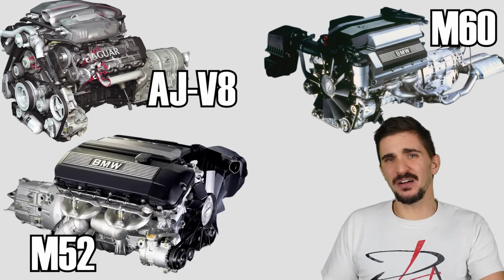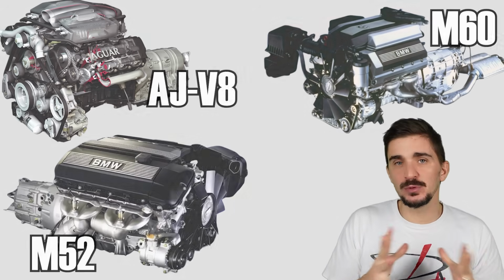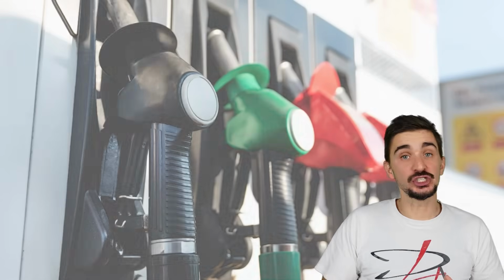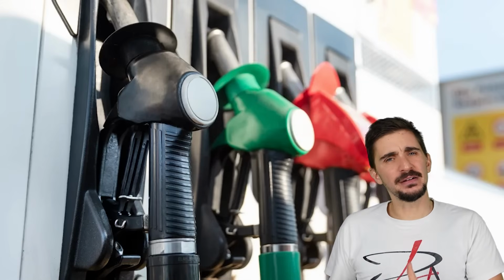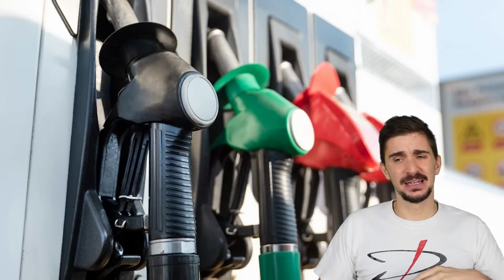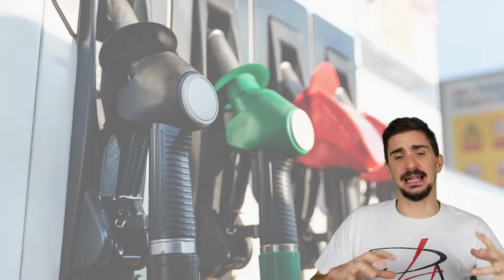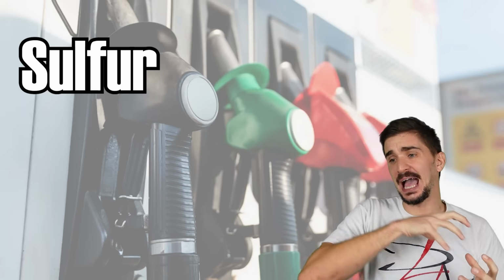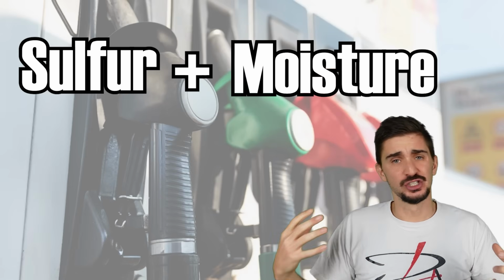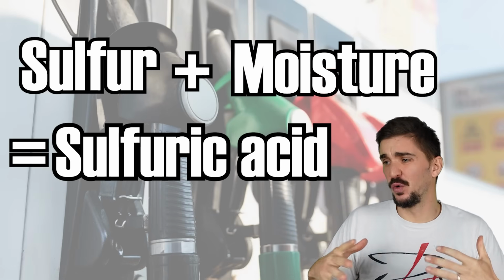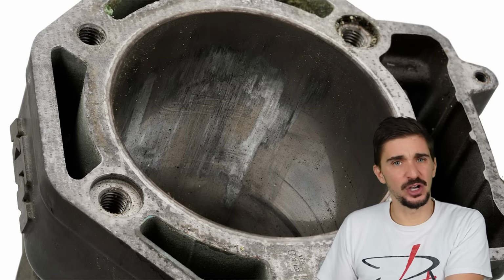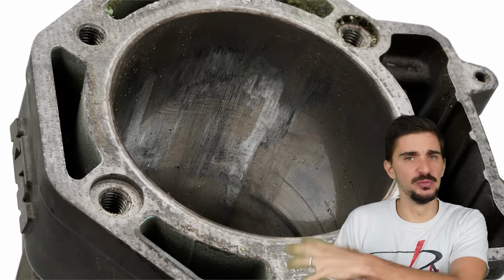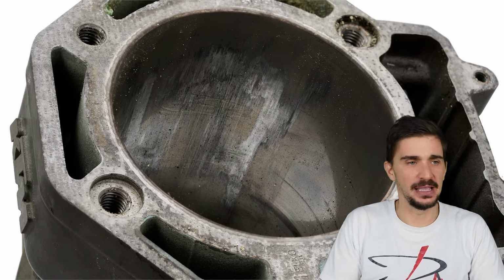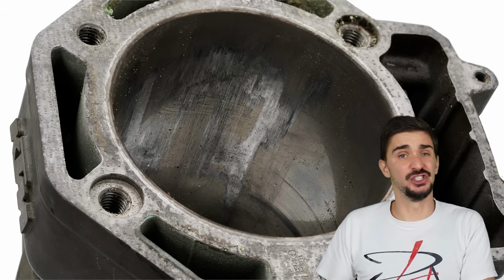However, it was soon discovered that Nikasil had a weakness. It was weak to high sulfur fuel, low quality, high sulfur content fuel. The most common explanation of the problem is that the sulfur in the fuel reacted with moisture to create sulfuric acid, which essentially over time dissolved the Nikasil coating. And without the Nikasil coating, aluminum has the wear resistance of a wet biscuit, and so the engine fails.